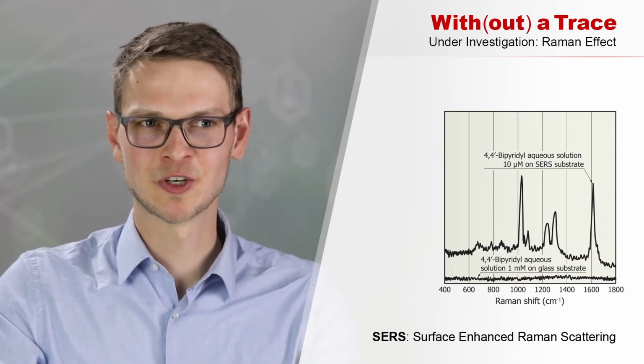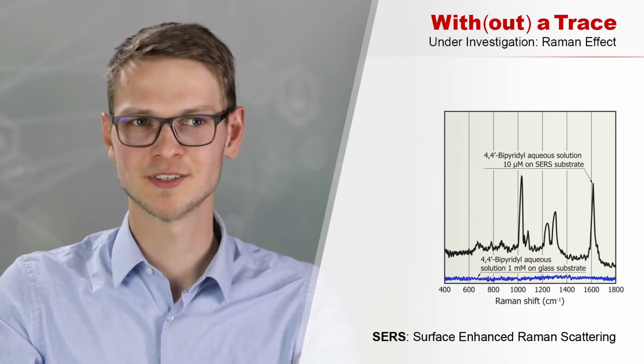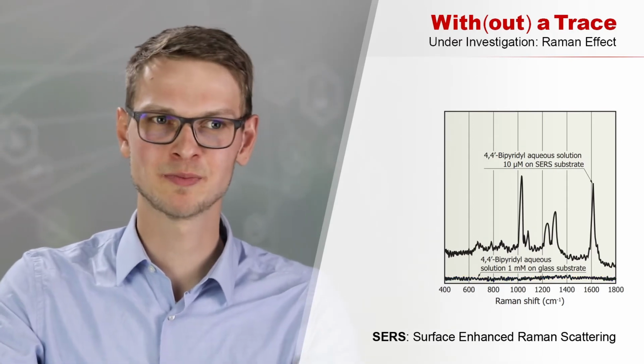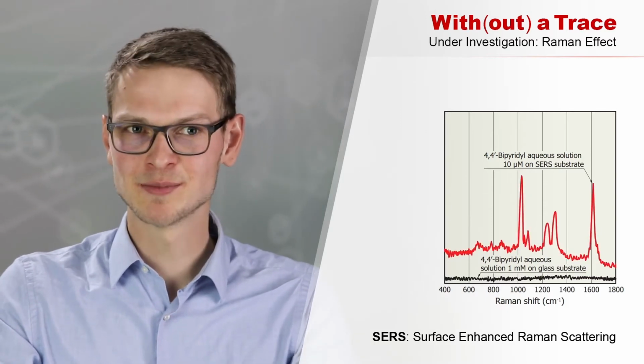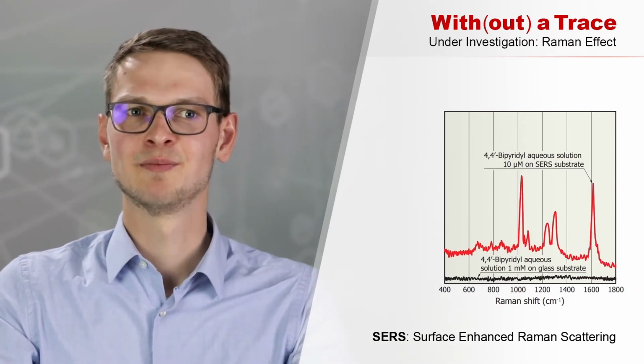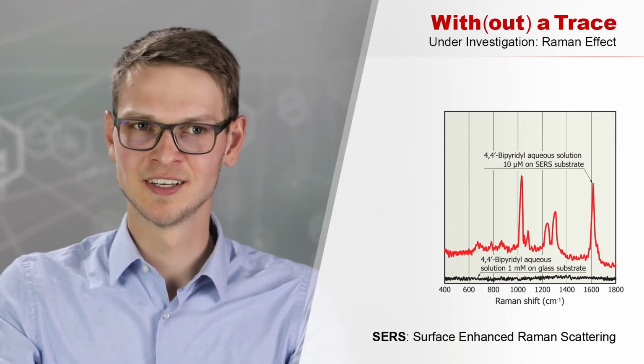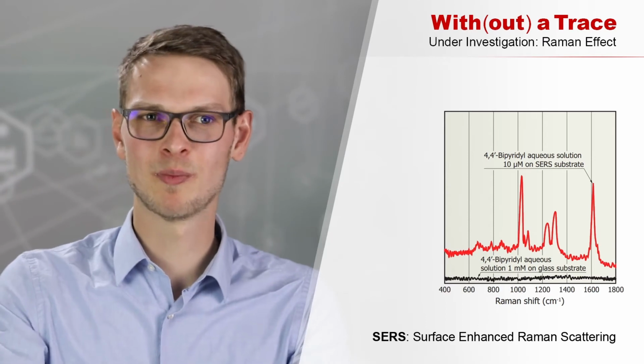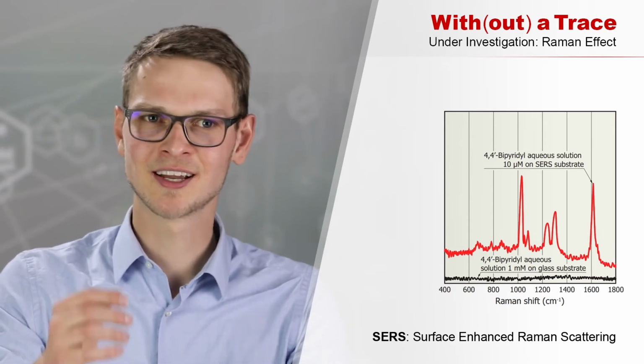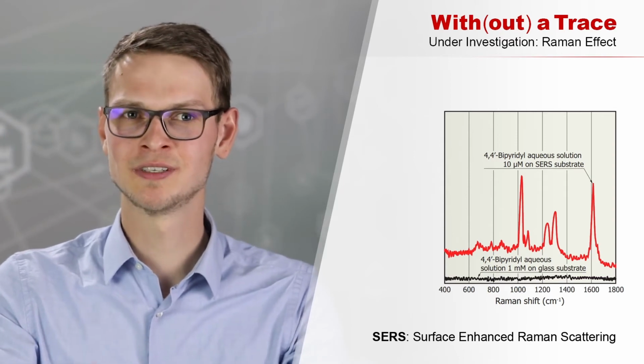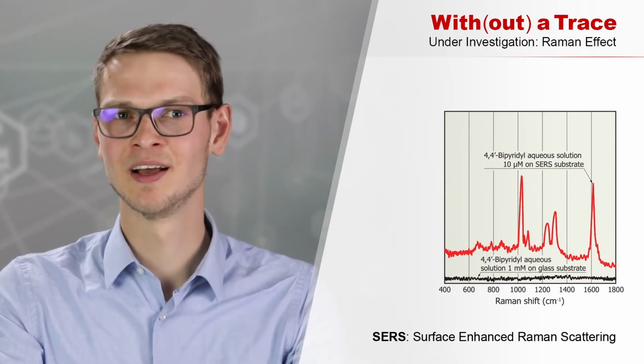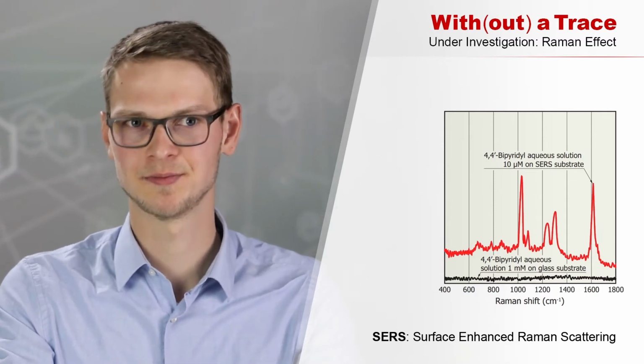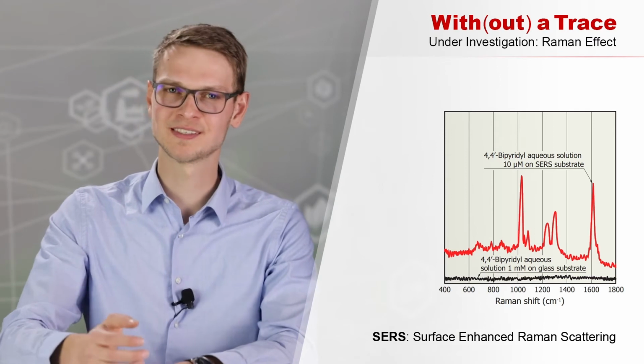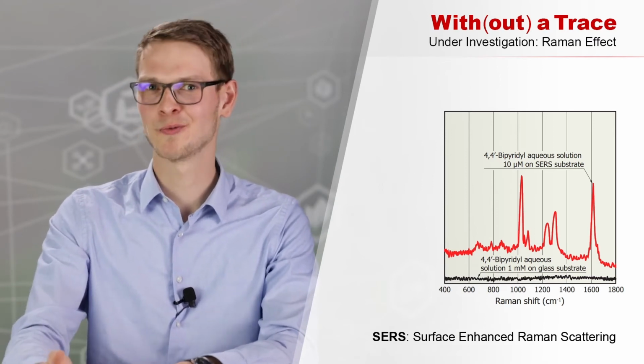It shows a spectrum of a bipyridyl solution, first on a regular glass substrate as the bottom spectral line, and second, the same solution on a SERS substrate. But please pay attention that the concentration of the solution on the SERS substrate is lower by a factor of 100. As you can clearly see, the solution is nicely resolved in the Raman spectrum if the SERS method is used. So as a take-home message for this method, if you have no success with regular Raman spectroscopy, you can also try the SERS method as an extension.